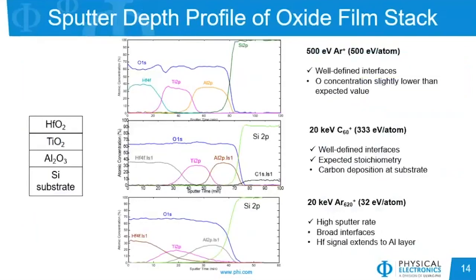And so the stack of materials that we're looking at is a hafnium dioxide on top of a titanium dioxide on top of an aluminum oxide on a silicon substrate. And the figure at the top is using our 500 eV monoatomic argon. The middle one is the 20 kV C60, and the bottom one is the 20 kV argon 620. And at first glance, we can look at things like the composition as we go through each layer. We can look at the interface quality, and we can look at the broadening that we may see.